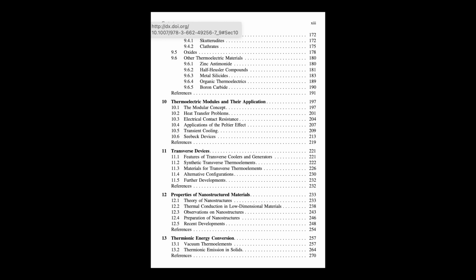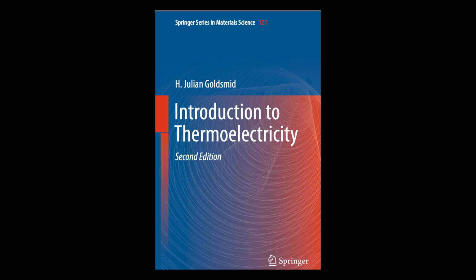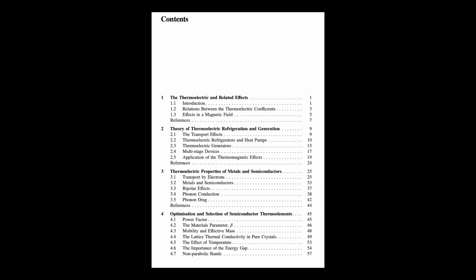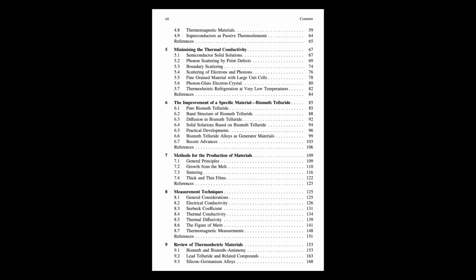Finally here, notes on bulk nanostructures and the measurement challenges for nanowires. Right, people are making bulk materials with nano features dispersed throughout, using techniques like mechanical alloying to create nanoparticles. This has shown some success in improving ZT in bulk, like in Bi-Te systems. But measuring ZT for individual nanowires is extremely difficult. Tiny size, making good contacts, measuring tiny temperature drops and voltages, it's a huge experimental hurdle. There have been successful measurements reported, like on electrodeposited Bi-Te nanowires, but sometimes the resulting ZT values weren't spectacular. Shows there's still optimization needed, and better measurement techniques are crucial.